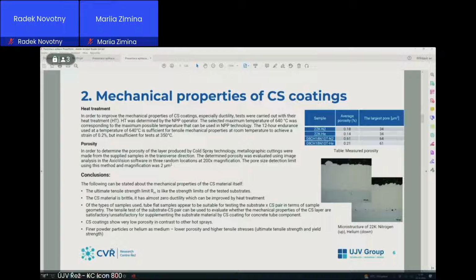So, conclusions are following. The ultimate tensile strength limit is like the strength limits of the tested substrates. So the results are for cold spray material itself. The cold spray material is brittle, it has almost zero ductility, which can be improved by heat treatment. On the types of samples used, tube flat samples appear to be suitable for testing the substrate and cold spray pair in terms of sample geometry.